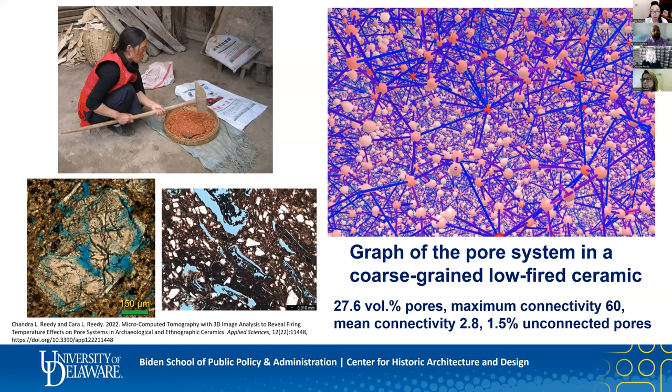The high connectivity can be partially explained by the partial burning out of organic material, dissolution of partially melted feldspars, cracking of quartz grains, and other kinds of firing effects on those large particles that tend to be more numerous in low-fired, coarsely prepared materials, as we see in the thin sections on the lower left here.